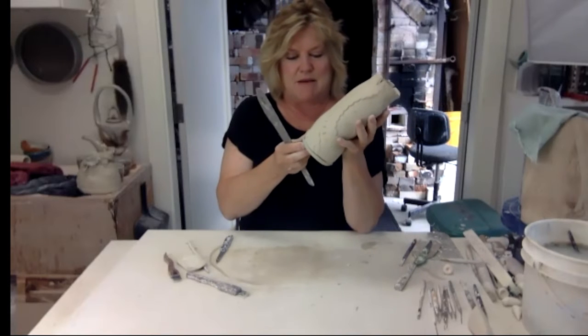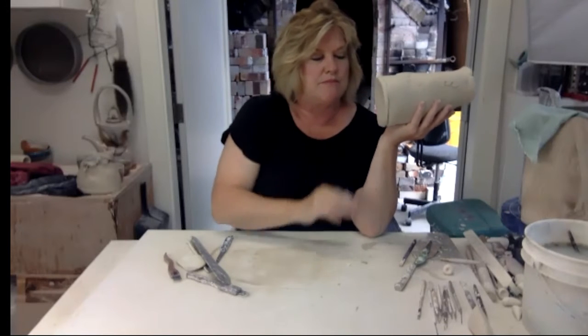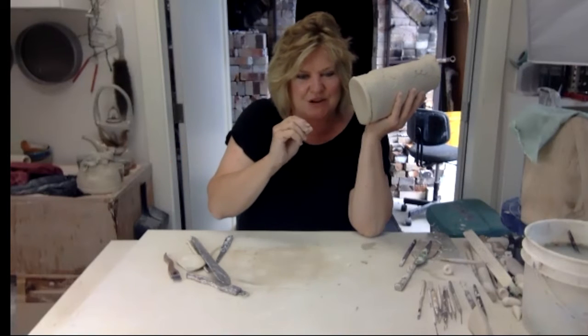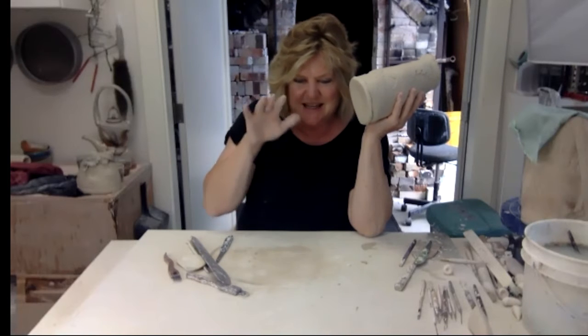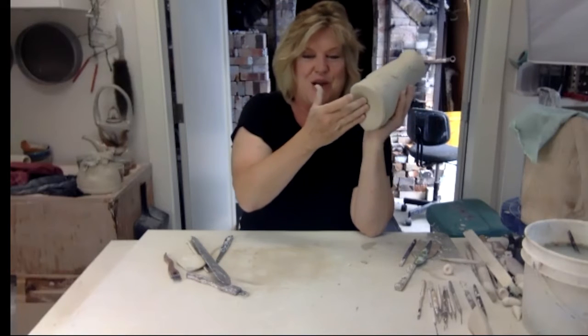Now this was that little spot right there. I also like this slab to be pushed upwards into the form. I've found it'll keep that slab from cracking, because as it dries, it will drop down. If it was flat, it has nowhere to shrink into, so it separates. You can expand on this, Ken, if you'd like. But that's why I do it. I've had more success with this being slightly